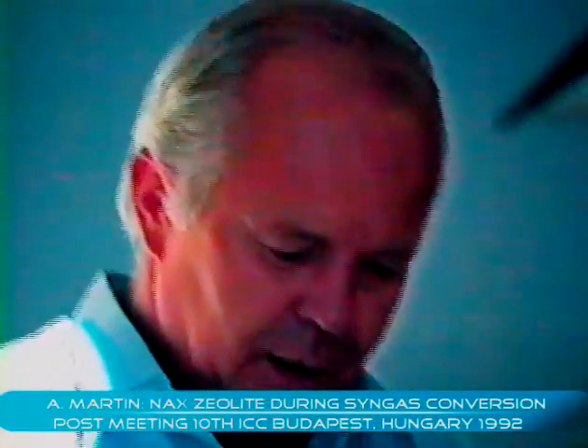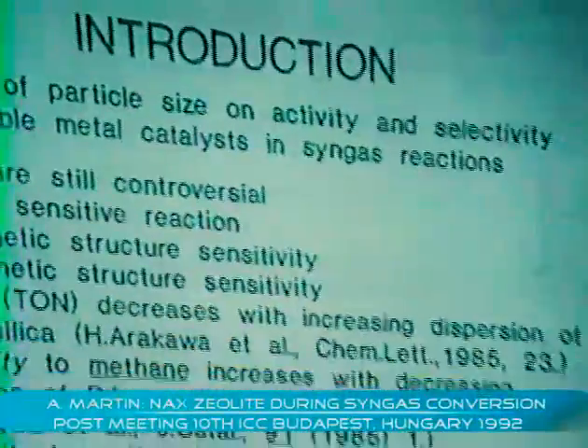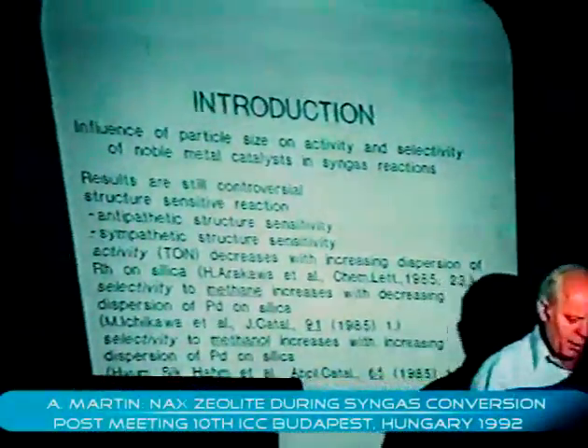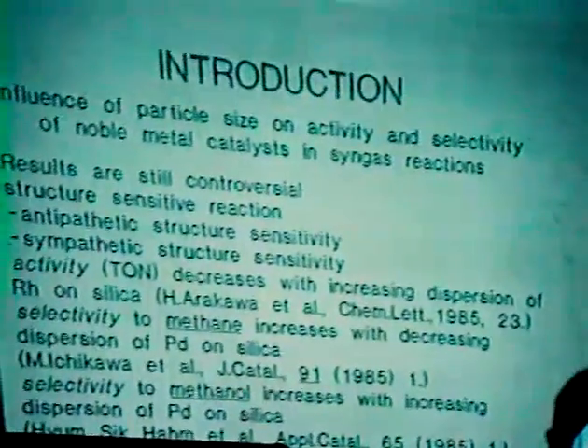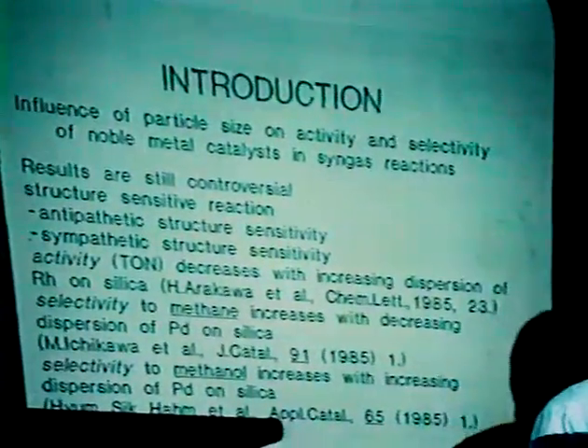For instance, Arakawa reported for rhodium on silica a decrease of the activity with increasing dispersion. And Bell, for the rhodium alumina system, found a decrease of the activity when the rhodium dispersion becomes larger than 0.7.